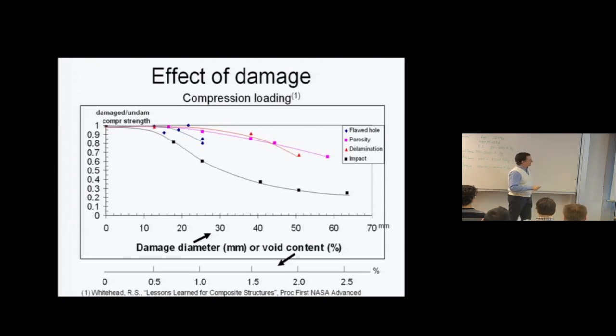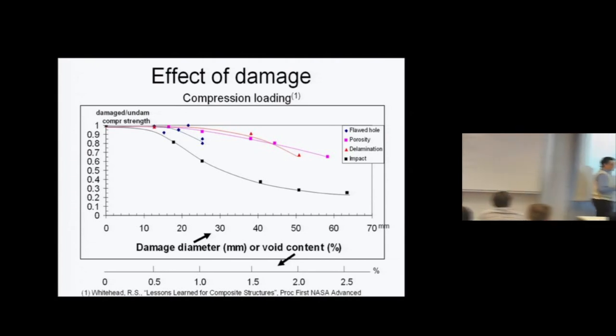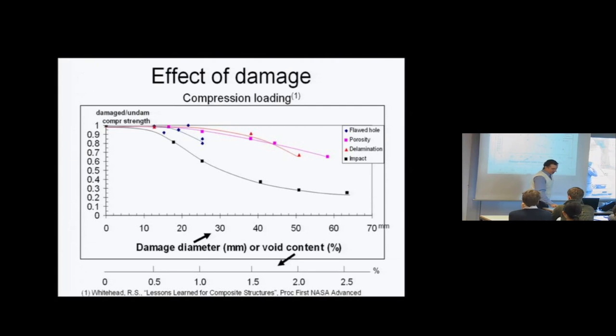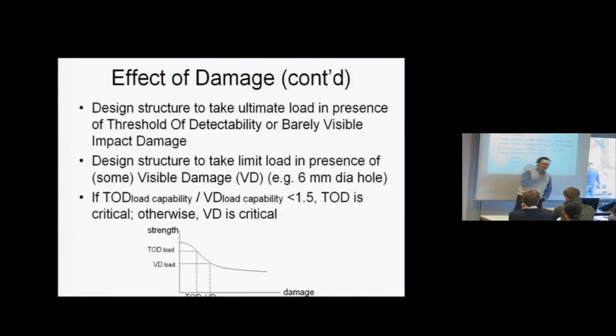And of course, impact. And shown here, the most critical one, this is first generation thermoset composite materials, where the reduction, as you can see, can be down to 60% or more. Newer materials are significantly above this curve, but as a rule, the impact damage tends to be one of the most critical types of damage.